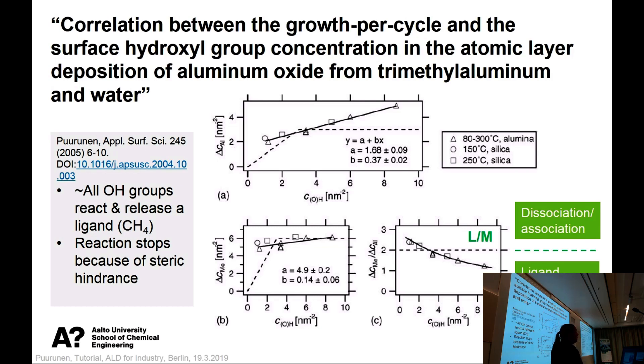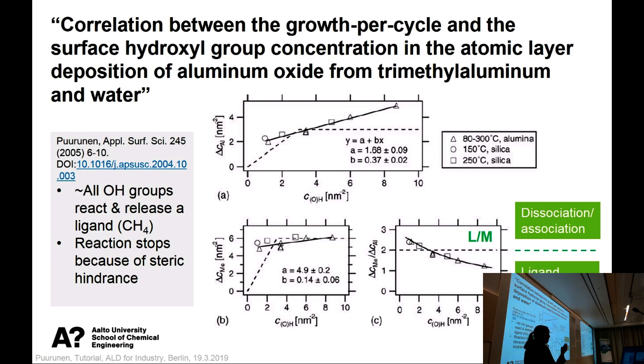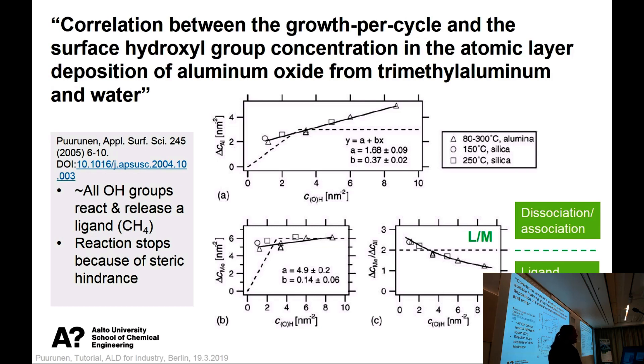My explanation — going through it very briefly — is that this process consumes all hydroxyl groups on the surface. Methyl groups want to combine with hydrogen to form methane. The reaction goes on as long as there is space on the surface, until we reach always about the same amount of methyl groups — roughly about 6 per square nanometer. That can be compared with the physical monolayer of methyl groups, which would be 7.2. So we are not very far off, and at least I can see that we have a highly dense methyl surface. This is not something that everybody would agree with — other ALD scientists might tell me something totally different. I think myself that this is one of the major contributions I have made to ALD.